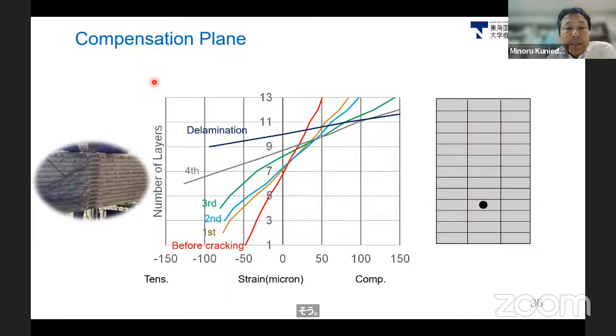And we also checked the compensation plane during the loading, and we put strain gauges on each filament, and then we checked the strain for each layer. Before cracking, a straight line in the strain was observed, and the first layer cracked, still straight, and then the second layer cracked, and the third layer cracked, and the fourth layer cracked. We observed the compensation plane. And in the final stage, even though it includes delamination of the layers, we have a straight line within the members.